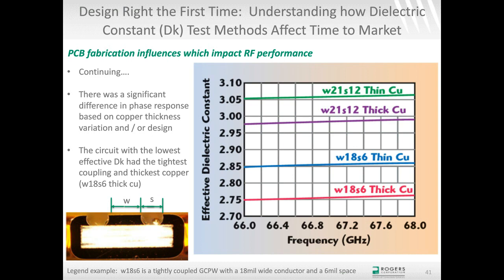Now, if you look at the exact same design, the W18S6, thick copper red curve, thin copper blue curve, there's a difference of 0.1 in the effective dielectric constant. And that's, again, using the exact same material, and the only difference is copper plating thickness. It's the same design in this case. And if you look at the loosely coupled design, that's the purple curve and the green curve, same designs again, same material, same everything. The only difference is thick copper, purple curve, green is thin.